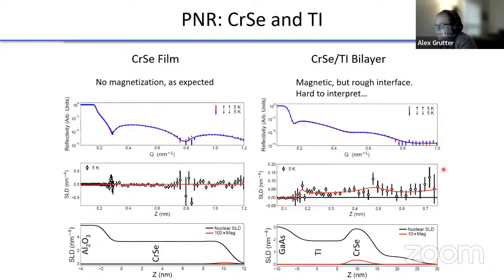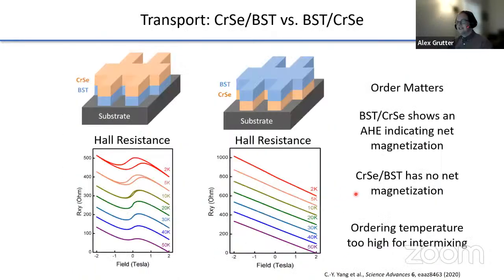The other thing I want to point out is it's much easier to understand what's going on in this system because, as I mentioned before, in the earlier example, almost all of your magnetic signal comes from your magnetic reservoir, your large ferromagnet that you grow. But of course, in an antiferromagnetic proximity effect, you're getting much less of a confounding signal from the magnetization of your proximity reservoir. Okay, so if we look at the transport data now, we actually got extremely lucky.